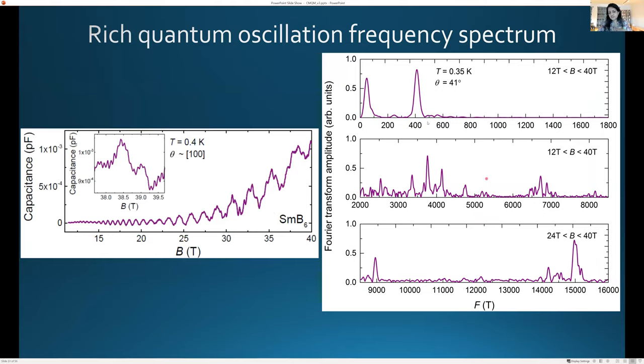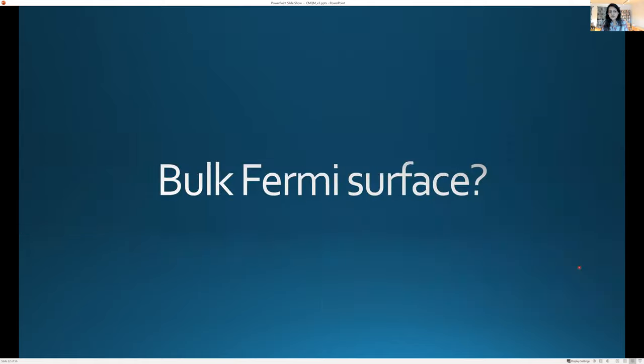And these are different field ranges. Sorry, this is a Fourier transform as a function of inverse magnetic field, which we do because the oscillations appear to be Landau quantized, so they're periodic in 1/B. So we take a Fourier transform in 1/B, and you get very sharp peaks, which is consistent with the inverse B periodic behavior. Okay. So the large size of the oscillation seemed to indicate it's a bulk Fermi surface, but we do a more quantitative comparison to check this.